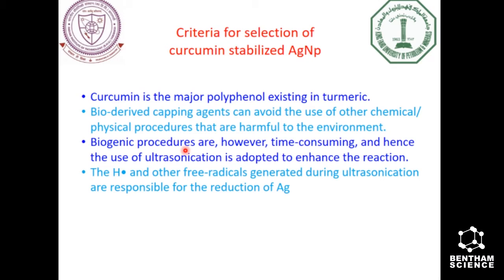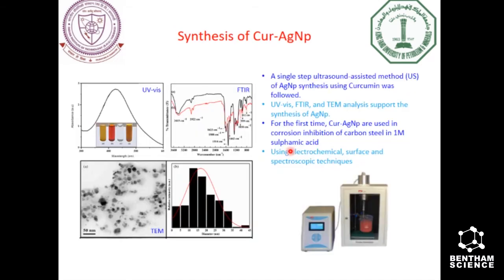The free radicals that are generated as the application of ultrasonication proceeds are responsible for the reduction of silver. The beauty of the ultrasound assisted method is that the synthesis was carried out in the single step method, and the synthesized nanoparticles were characterized using UV visible, FTIR and TEM analysis. And for the first time, we used the curcumin capped silver nanoparticles as corrosion inhibitors for carbon steel in 1 molar sulfamic acid using a detailed analysis of electrochemical, surface and spectroscopic techniques.